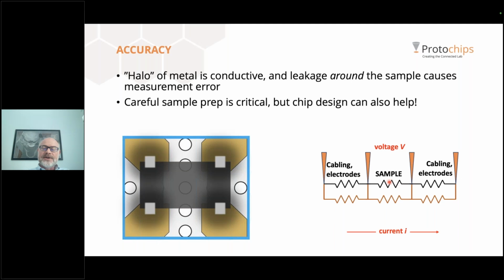So the key here is to avoid the overspray of metal that can lead to current paths around the sample and confuse your measurements. People have reported that tungsten is sometimes preferred to platinum because it has less overspray. You can actually change the metal deposition conditions completely to mitigate this somewhat. Sometimes you can make your FIB cut larger, and this is now even more possible due to the rise of plasma FIBs that are faster and cleaner.